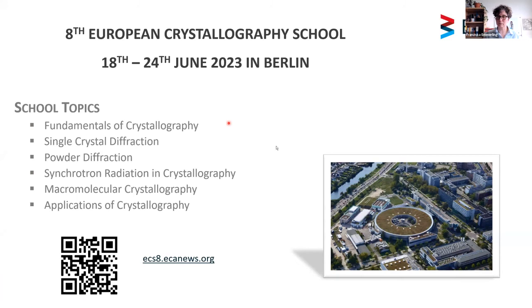And that's kind of related to a question that came up in the chat about generally determining structure from powder diffraction. I was just amazed at the quality of the diffraction patterns that you're getting. You mentioned comminution. Clearly, there's some kind of significant recrystallization process to give you nicely crystalline materials that you can use in Rietveld refinement. So when we solve the crystal structure from powder diffraction data, we use the as-synthesized material. So there is not a recrystallization step in between.